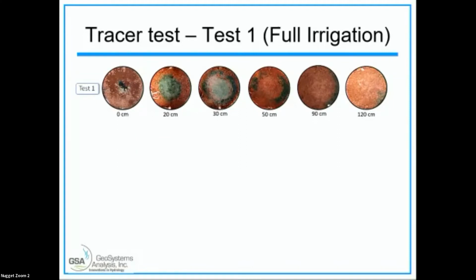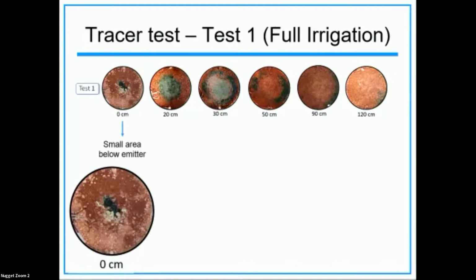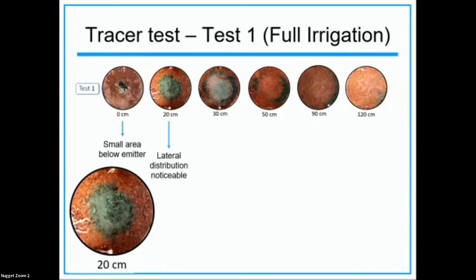And so at 0 centimeters next, we see a small area just below the emitter that was wet, even though the whole thing had collapsed. So it's like, what's going on? At 20 centimeters next, you could see that there was quite a bit of lateral distribution. And so there was wetting through most of the center of the core. Next.